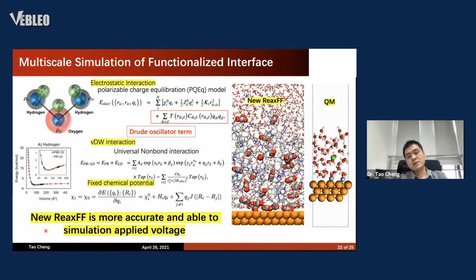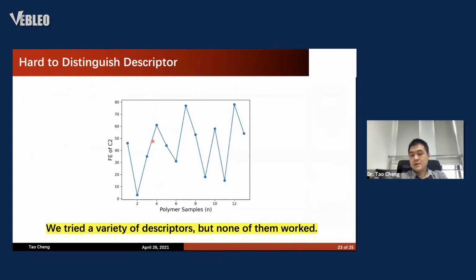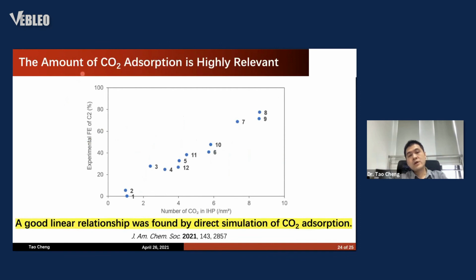In this case, we developed this new reactive force field that can both accurately account for the applied voltage and is also affordable for simulating a large system like this one. We then simulated the interface, and we are trying to correlate the structure to the performance. But we have to say that after many tries, we all failed. We could not find a very good descriptor. But finally, we found that if we used the number of CO2 adsorbed on the surface, we can actually have a very good correlation. Here, the x-axis is the number of CO2 on the surface, and the y-axis is the performance. We can see an almost perfect linear trend here.